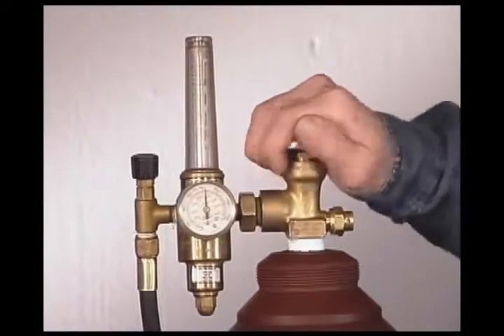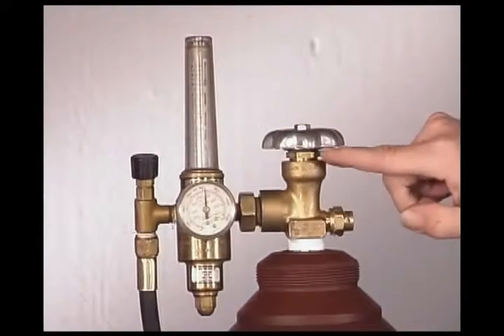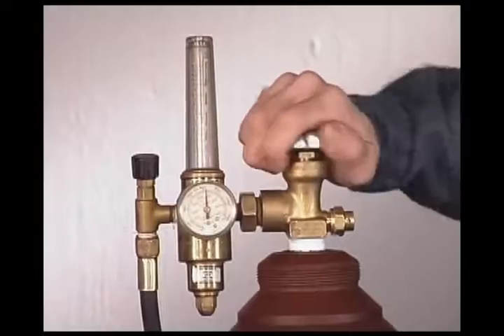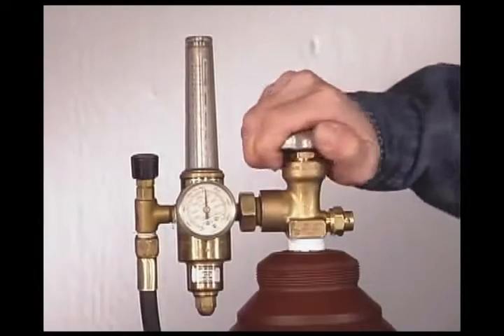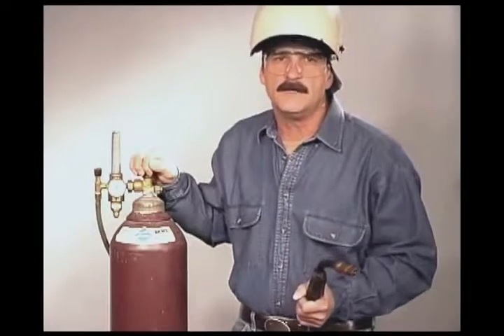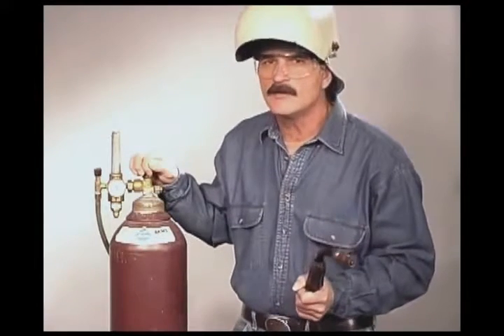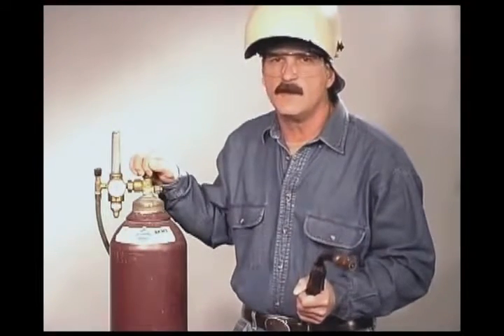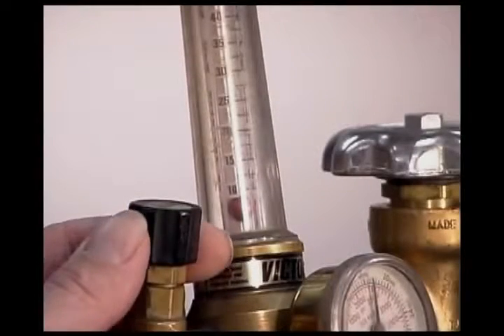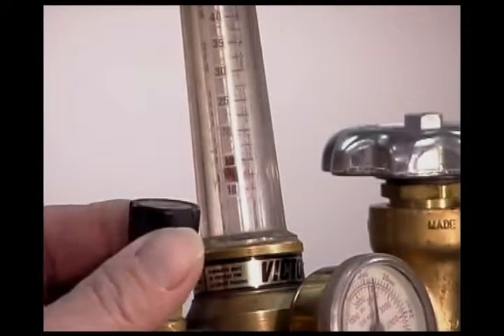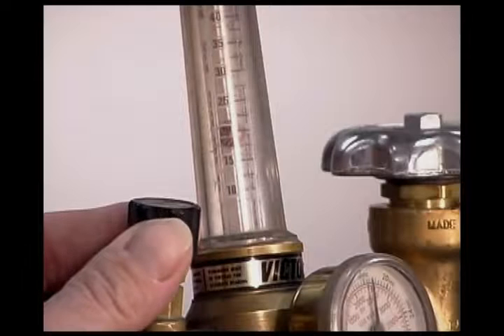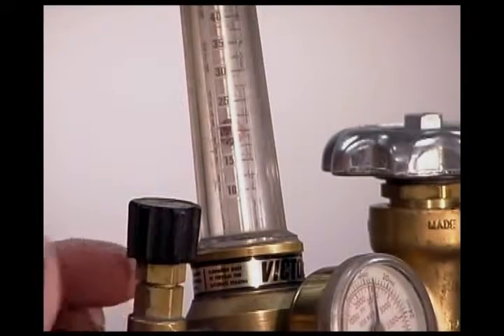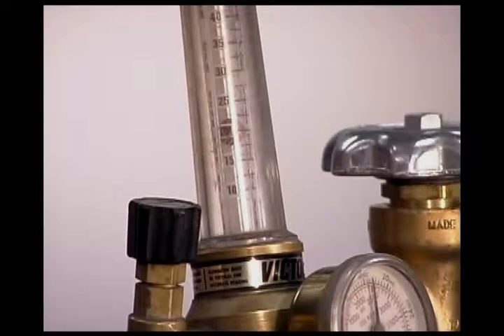High pressure valves have two seats, one to close the bottle and the other to seal the valve stem when the bottle is open. So open the valve all the way. Regardless of the style of flow meter you're using, you get a more accurate adjustment with the gas flowing. So pull the trigger on the gun. Ideally, you want to use the minimum amount of gas that it takes to cover the molten weld, usually around 20 cubic feet per hour.